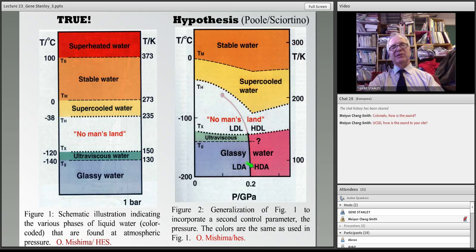And what they discovered is that this line of first-order transitions between the two forms of glassy water extended into the no man's land, separating now not glassy water, but two liquid water phases, a low-density liquid, LDL, and a high-density liquid, HDL. And this line of transitions extended smoothly, and then stopped. This was a line of first-order transitions, just like this is a line of first-order transitions. And many of you know that, with a few exceptions, but very few, lines of first-order transitions terminate in critical points, just as we saw a minute ago, where the liquid-gas transition in water terminated at its liquid-gas critical point, so also the LDL-HDL transition terminates at a critical point above which there's no difference between LDL and HDL.